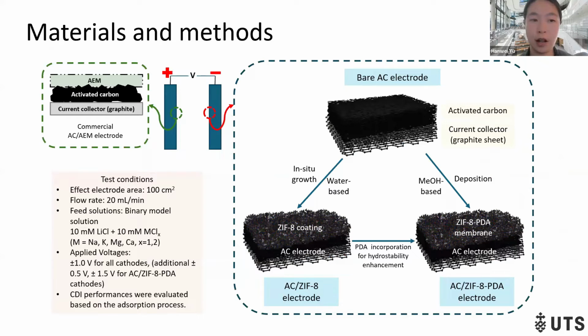So in this research, on the commercial AC electrodes, I coated the ZIF8 type of MOF. First, I used the water-based in situ growth method, and a double layer of ZIF8 was coated on the electrode. However, due to the poor water stability of ZIF8, to enhance it, I incorporated polydopamine to enhance the ZIF8's water stability. I used the deposition method to coat a layer of ZIF8 polydopamine membrane on the AC electrode.